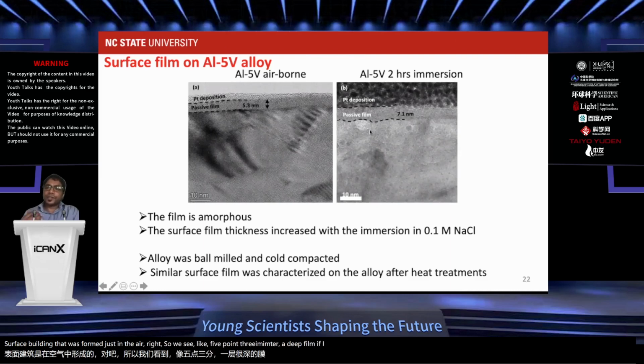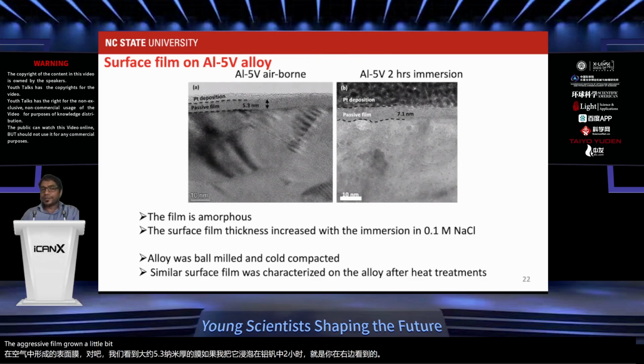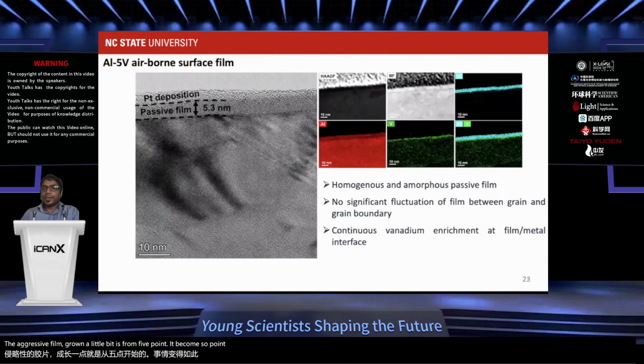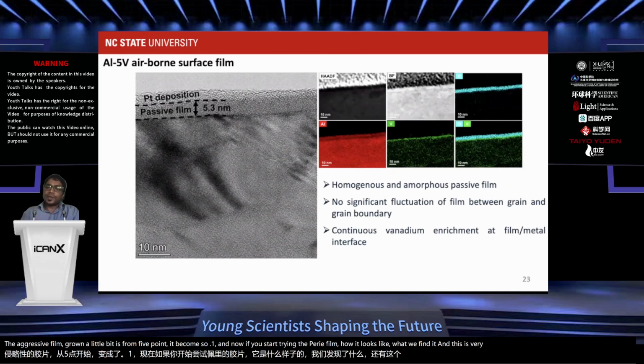If I immerse it for 2 hours in aluminum 5 vanadium, the one you see on the right, the passive film grew a little bit. From 5.3, it becomes 7.1. And now if you start characterizing the passive film, how it looks like, what we find is, and this is a very specific example for aluminum 5 vanadium alloy.